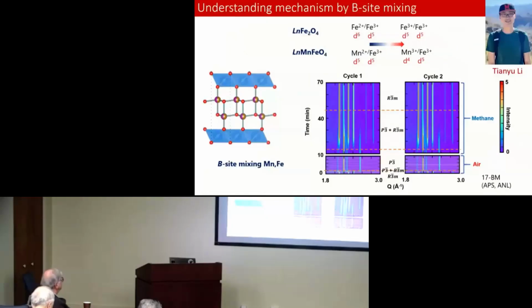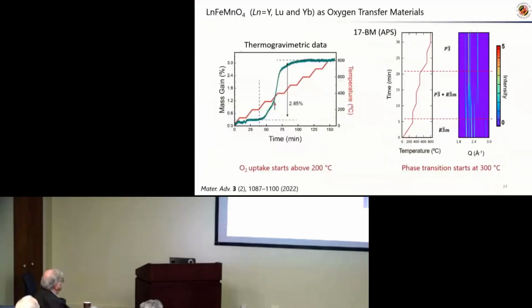Then my student Tianyu Li played around instead with the B site, putting in iron and manganese, a B site mixing type of material. We do powder diffraction as a function of time and follow the oxidation. This is, again, a synchrotron data set. What's remarkable about these materials is that they start oxygen uptake at about 200 degrees Celsius.